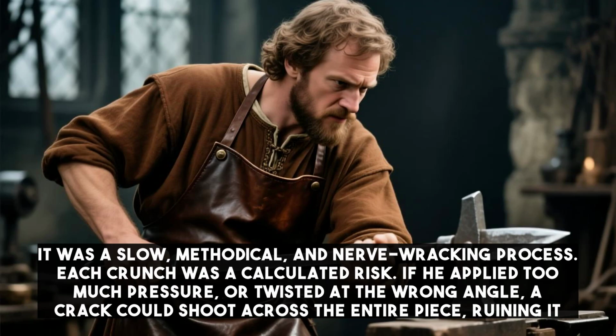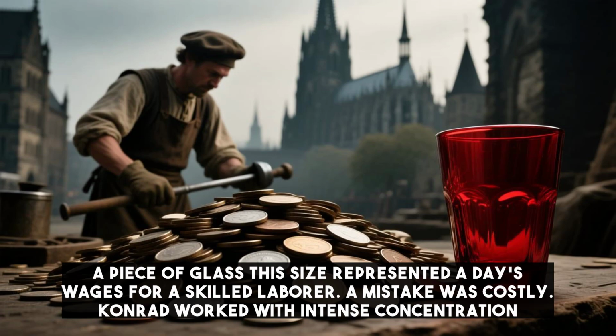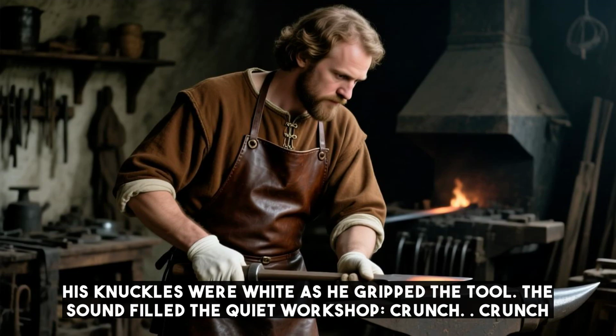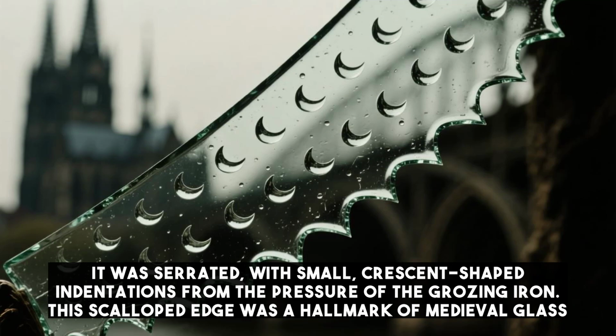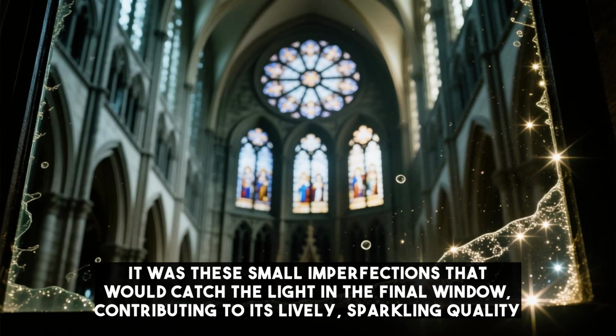Each crunch was a calculated risk. If he applied too much pressure or twisted at the wrong angle, a crack could shoot across the entire piece, ruining it. A piece of glass this size represented a day's wages for a skilled laborer. A mistake was costly. Conrad worked with intense concentration. His knuckles were white as he gripped the tool. The sound filled the quiet workshop. Crunch. Crunch. The edge was serrated with small crescent-shaped indentations from the pressure of the grozing iron. This scalloped edge was a hallmark of medieval glass. It was these small imperfections that would catch the light in the final window, contributing to its lively, sparkling quality.